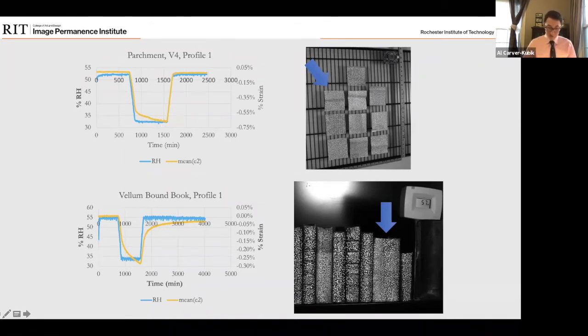And this is true for both the single sheets of material, which is shown at the top, and the bound volume, which is shown at the bottom. These are a parchment sample and a vellum bound book. When the RH returns to 50% relative humidity, the materials respond again by absorbing moisture, returning to or near 0% strain. So you can see we come back to where we started. It's returning to the size it was in the beginning. And the general pattern is similar to all the single sheet materials in all of the books tested.